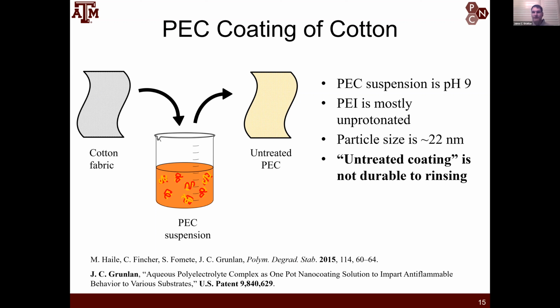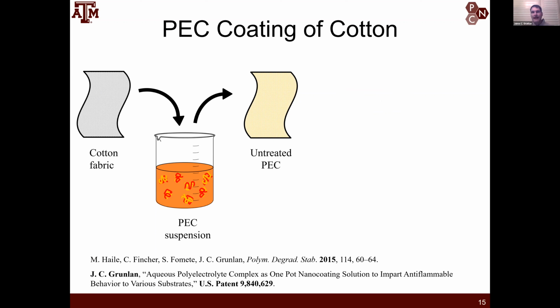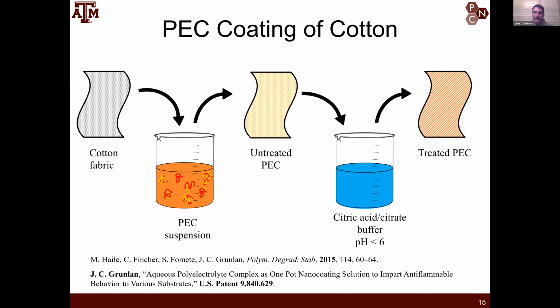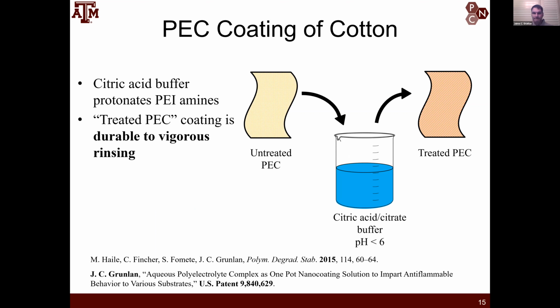So in this example, I take cotton fabric, I dip it into this polyelectrolyte complex suspension. PEC means polyelectrolyte complex. And then when I, as a second step, dip that same textile into a buffer solution, here it shows pH less than 6. It would depend on the chemistry that you're working with. But in this specific PEC, the pH less than 6 buffer caused the complexation on the textile to make a very uniform, conformal coating on the cotton.